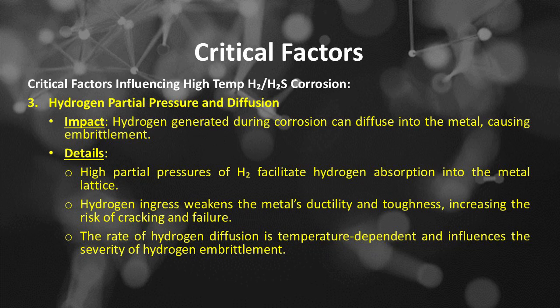Critical factors. Number 3 is hydrogen partial pressure and diffusion. The hydrogen partial pressure and diffusion impact. Hydrogen generated during corrosion can diffuse into the metal, causing embrittlement. For details, high partial pressures of H2 facilitate hydrogen absorption into the metal lattice. Hydrogen ingress weakens the metal's ductility and toughness, increasing the risk of cracking and failure. The rate of hydrogen diffusion is temperature dependent and influences the severity of hydrogen embrittlement.